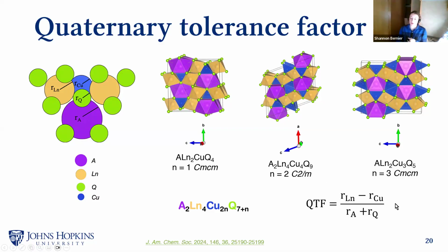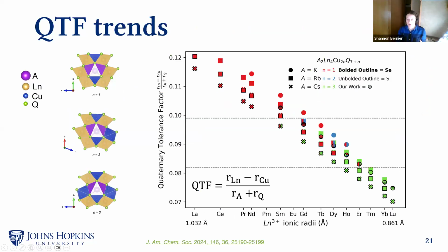So this is the quaternary tolerance factor, QTF, based on the radii and approximate packing of these 3 structures that Greg's group developed. And when you apply it to materials, it looks like this. So on the bottom axis here, we have the radius of the lanthanide, and we have tried different substitutions of that lanthanide. So here we have large radius on the left and small radius on the right. The value of this QTF is vertically here. And as you can see, the QTF successfully sorts these into a region of high QTF value, which corresponds to large lanthanide radius, where the materials will crystallize in the n=1 space group.